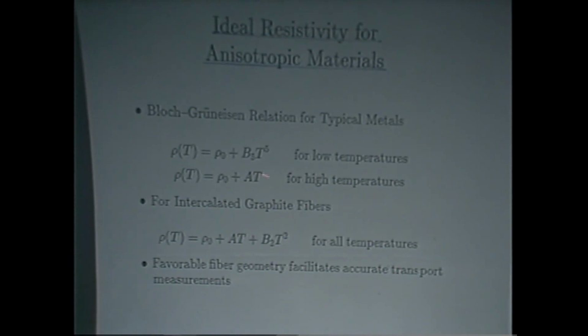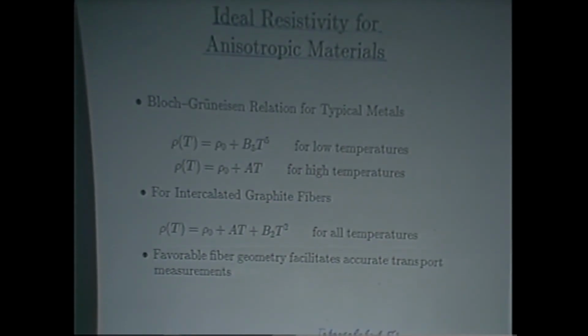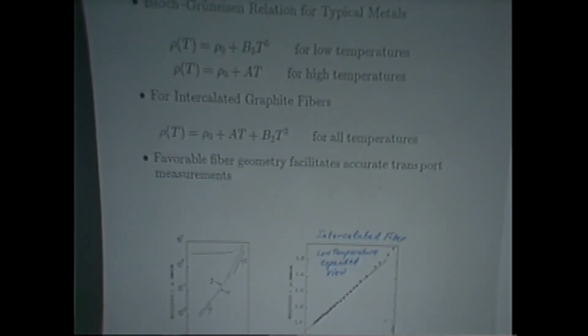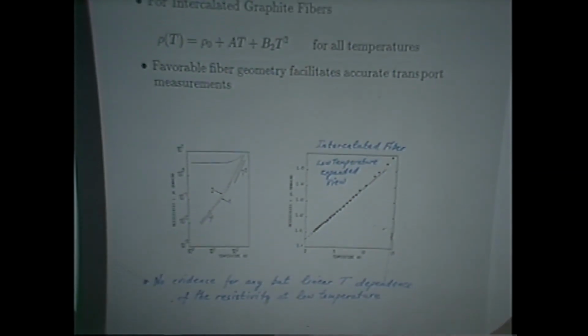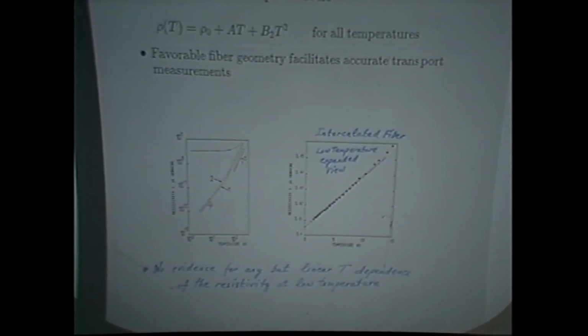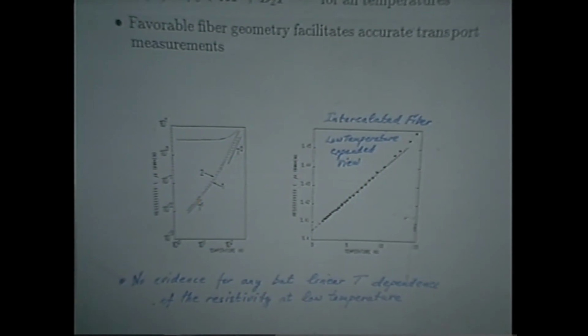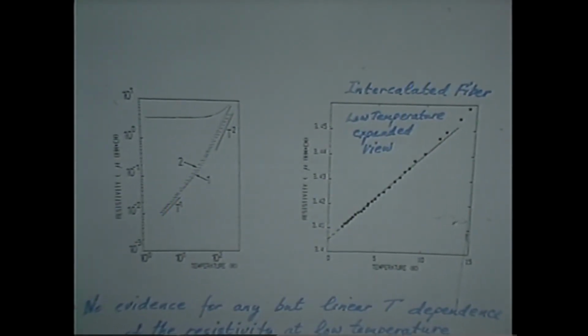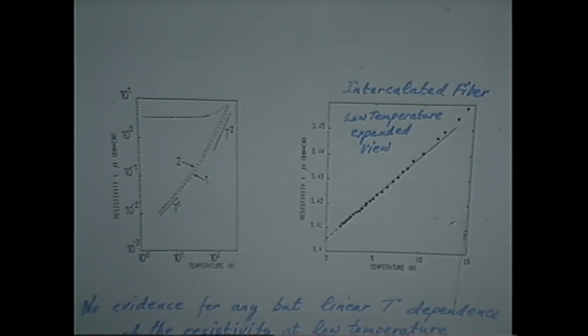And at high temperature, there's this linear relation that everybody sees. That's not unusual. But with these fibers, you can actually make a very accurate measurement at low temperature of what the temperature dependence is, and it works well in intercalated fibers. And down at low temperature, it's linear. But that's a two-dimensional system, so Bloch-Gruneisen might still be right. But I'm not sure how right it is.